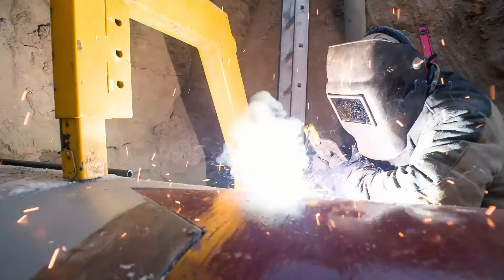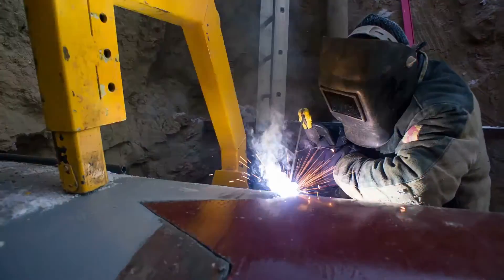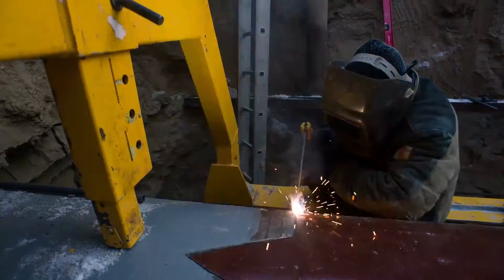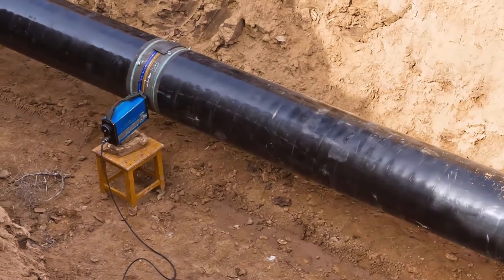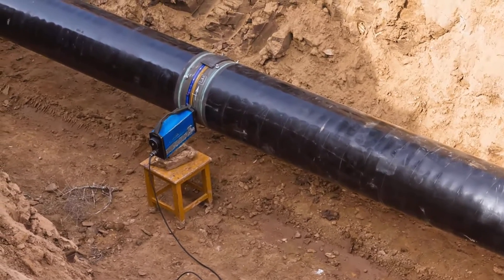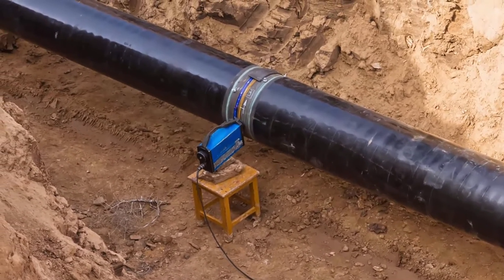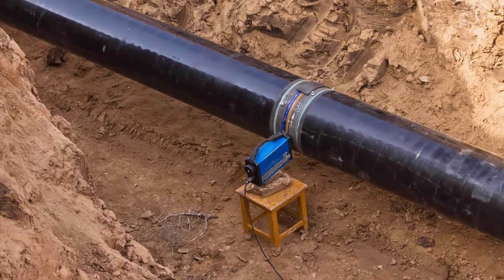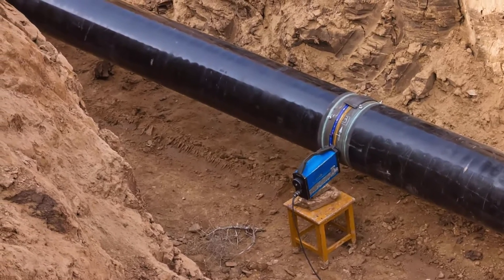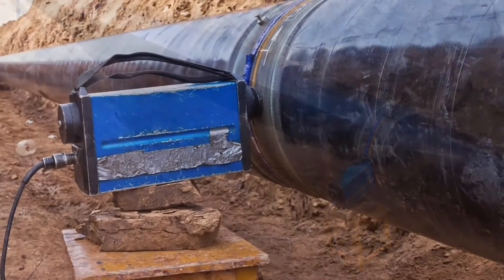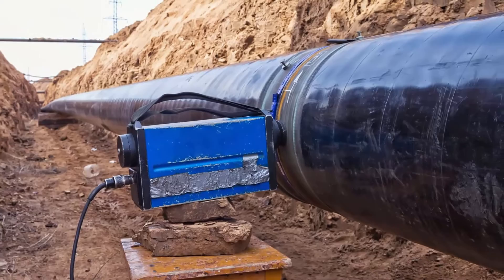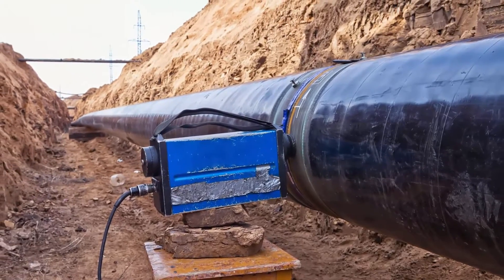Most construction codes require complete volumetric examination of a welded joint and the heat affected zone in the manufacturing process. For decades, industrial radiography has been the commonly used examination technique, but this technology has several drawbacks. RT is insensitive to some misoriented planar defects, it does not provide immediate feedback to the welders, and it is disruptive to other construction activities.